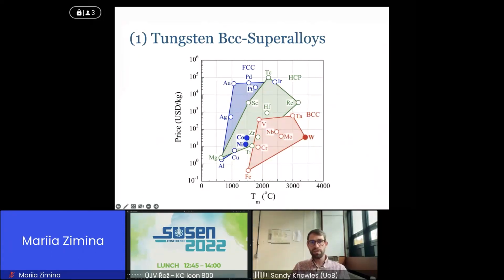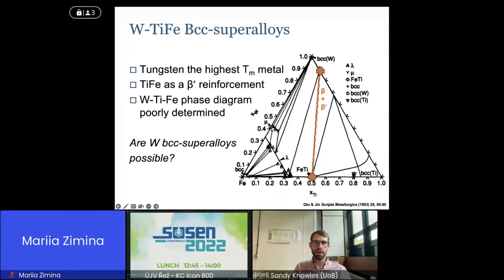So we've been applying this BCC superalloy concept to another system. We previously worked on titanium alloys, and then, as I was mentioning, around this Eurofusion project we had on nanostructured tungsten, we wanted to have tungsten with precipitates. So we tried to see if we can apply this BCC superalloy concept. So we got the motivation of BCC as high melting point. Essentially, this beta prime could be a reinforcing phase, but we also have interest in terms of the interfaces towards radiation damage. Well, the challenge we had is that there wasn't very much prior study of this system.